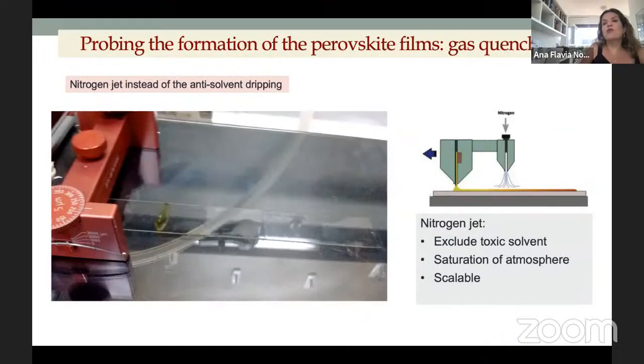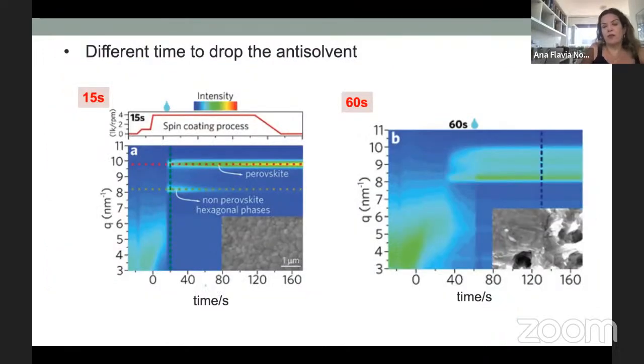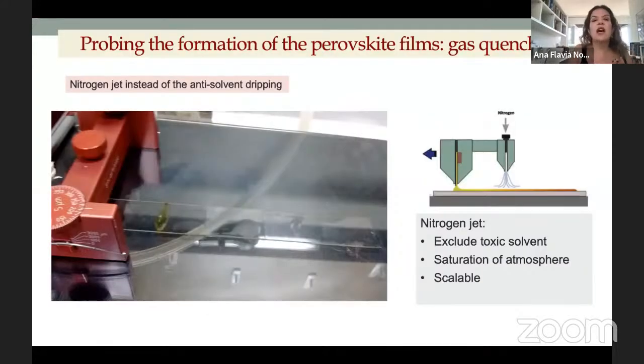But then we decided to move to another deposition method, because as I mentioned before, in these methods everything is done manually inside of a glove box. So nowadays, this is the method that we use to deposit our perovskite, what we call gas quenching. What is this gas quenching? Instead of using chlorobenzene as the antisolvent, you can use, for instance, nitrogen, okay?